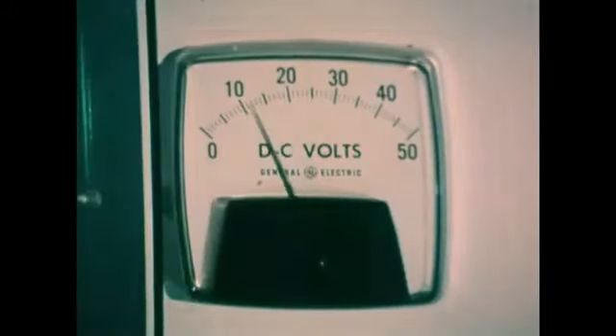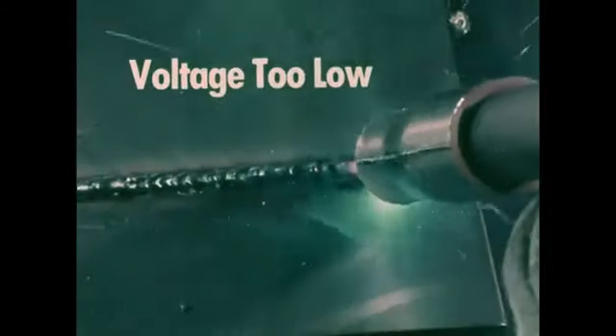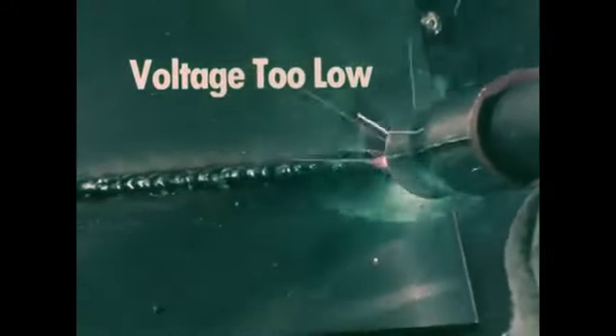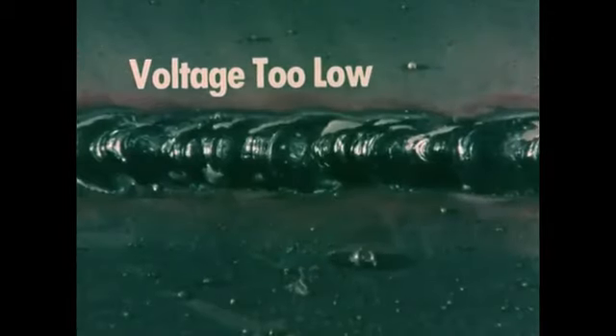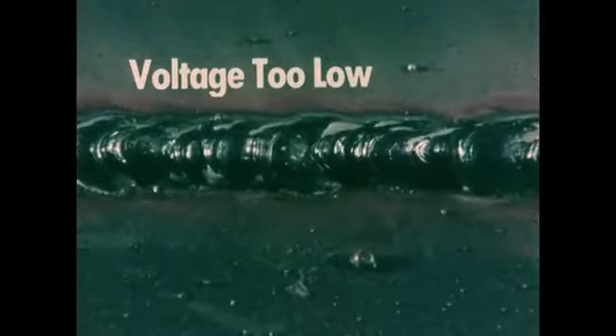Lowering the open circuit voltage to 20 provides a load voltage of 12 or 13. The deposition of filler metal is irregular. The weld joint has a high crowned bead. Very little penetration is achieved. Rather, the metal deposit is mostly on the surface.